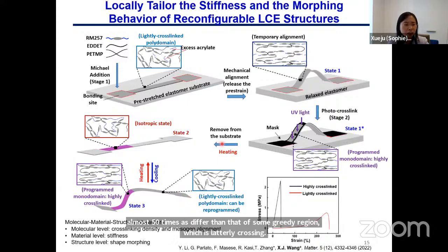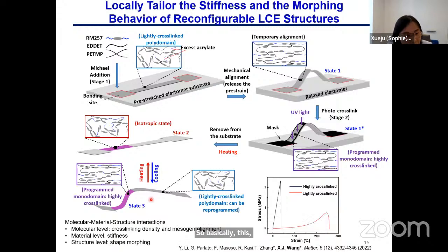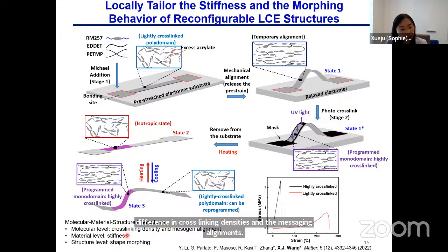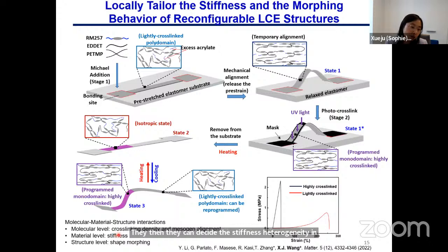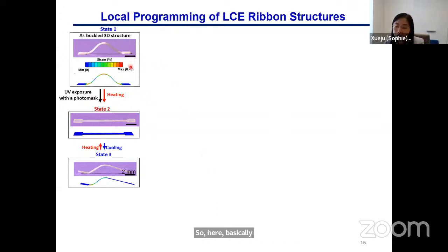So this interesting asymmetric structure is achieved by harnessing molecular-material-structure interactions. By selective photopolymerization, we can create a difference in cross-linking densities and mesogen alignments. Then they determine the stiffness heterogeneity at the material level, and the material-level stiffness heterogeneity and the molecular-level mesogen alignment can synergistically create the local shape morphing behavior of the structure. Here are the experimental and finite element analysis results of the local programming of LCE ribbon structures, which can start from an arc shape and then morph to this asymmetric structure after selective programming.